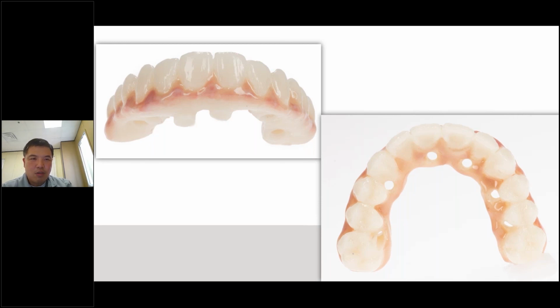But for people who don't have those, if you have Noritake ceramic, you can just use the same glazing paste, mix it up, paint it on there, and then create the lobes. You can create perikymata, you can create developmental depressions by adding depth into the same tooth structure. That gives you the effect that you need without having to do any more micro grinding or micro layering on your porcelain. Everything is pretty much done beforehand. Even on the same areas of pink, you can polish them down, give you the same effect that you want, and give it the look that you want just by applying this. This is actually all done in about 3 powder build-ups. We did not have to do anything to the ceramics because this is pretty much the material itself coming out.